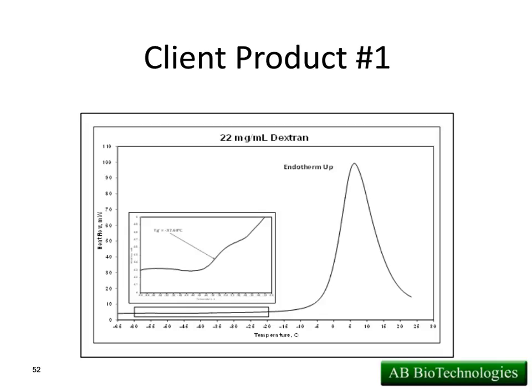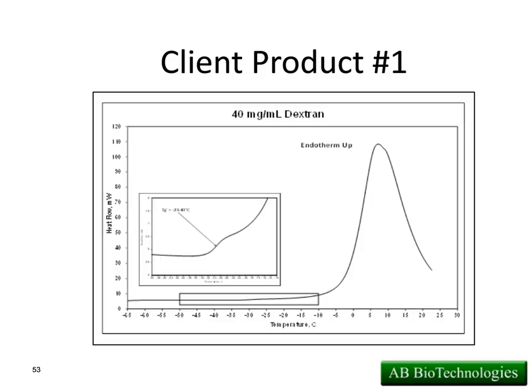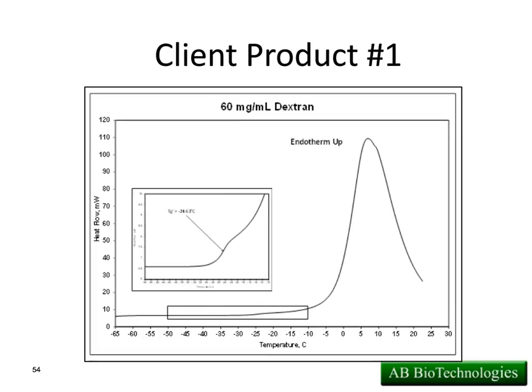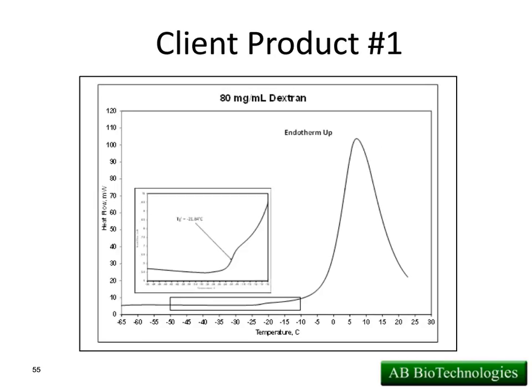So we're not there yet, but we're definitely seeing an improvement. Okay, we blended in a little more, and in this particular case, we got it up to 40 mg per mil. Now we're up to negative 29. So again, we're having an improvement here by blending in increasing amounts of that dextran. Okay, by adding 60, we're now up to negative 20, almost 25, and that's perfect. Freeze-drying something at negative 25 is well within the limits of what we can consider acceptable. We even took it one step further and took it up to 80 mg per mil and got it up to about negative 22. Now, this is great.